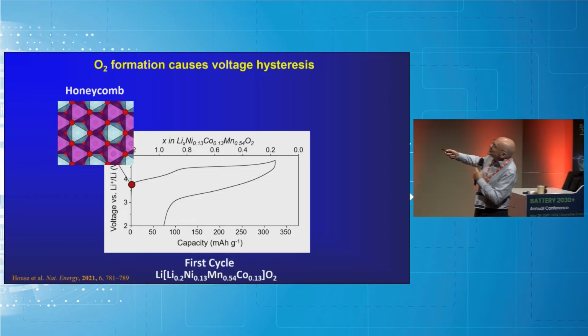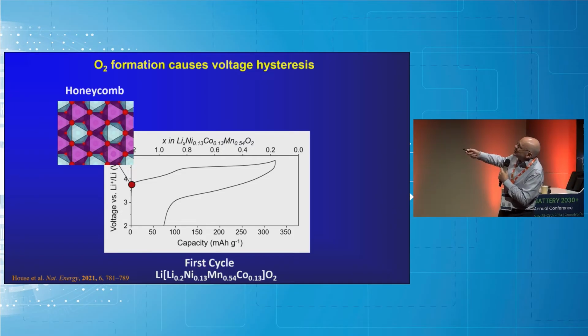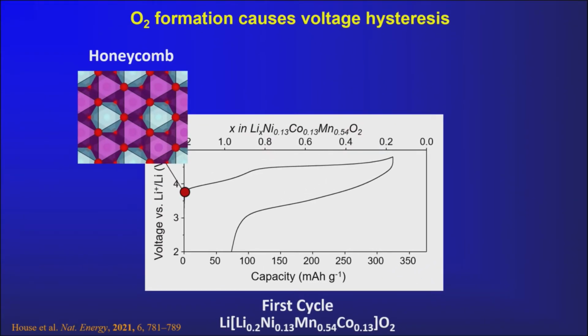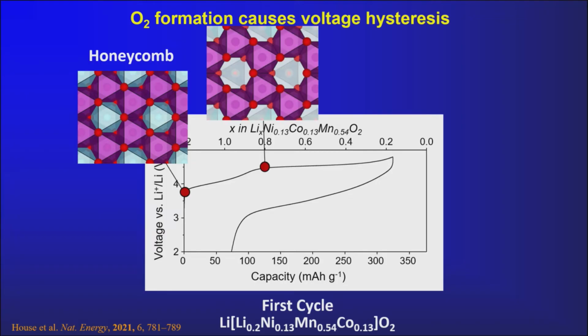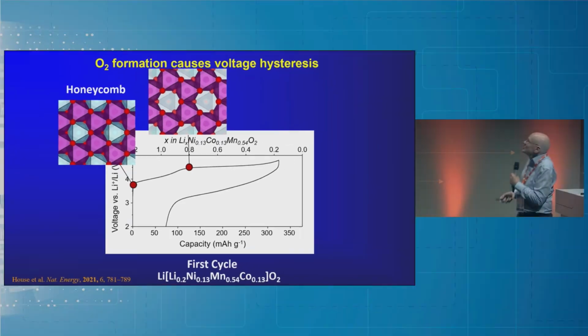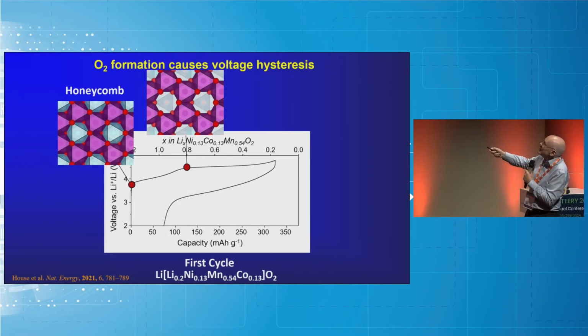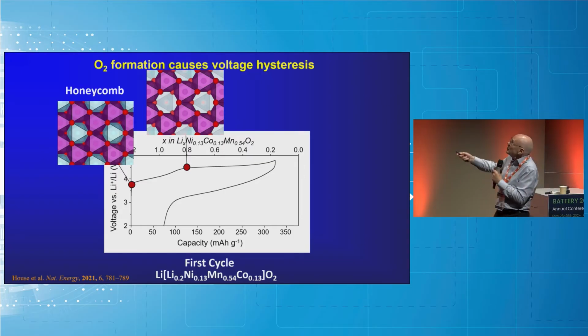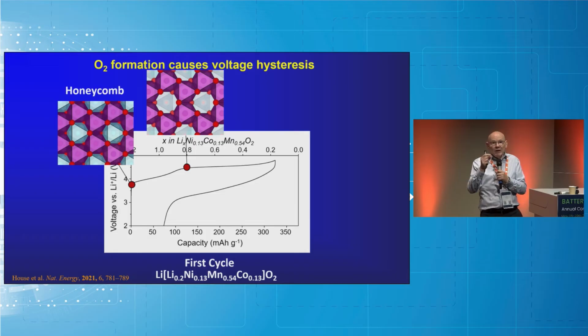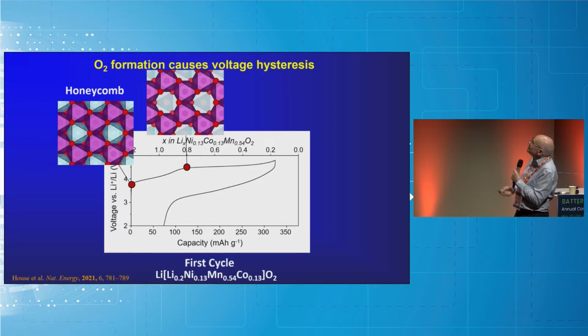So this is what happens. Here's our pristine material at the beginning. There's the transition metal layer, just one color now for the transition metal ions, and the light blue octahedra represent the lithiums. And they're going to be depopulated as we charge. So we charge up to the beginning of the plateau. Some lithiums come out of the alkali metal layers, some come out of the transition metal layers. That's represented by these vacancies here. Then when we go across the plateau, so far we've just balanced this loss of lithium ions by oxidizing transition metals. Now we're going to oxidize the oxide ions.